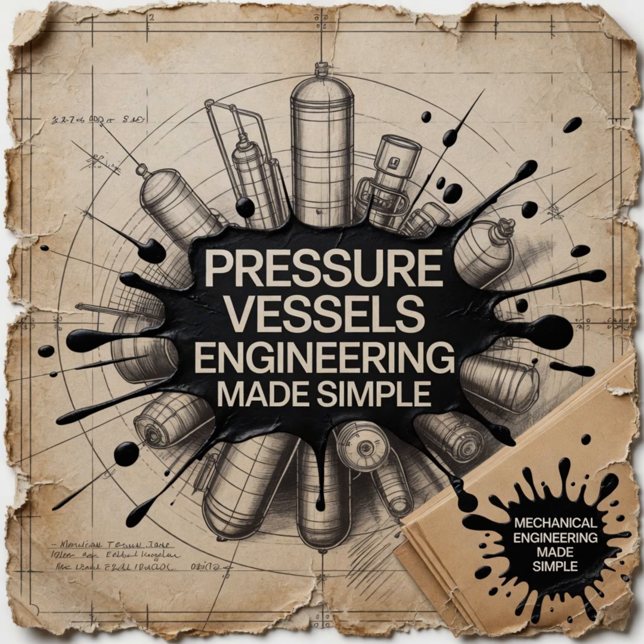Designers use stiffening rings. These are heavy steel I-beams or thick plates welded edge-on around the outside circumference of the vessel. What do those rings actually do? What these rings do is effectively break one long, mathematically vulnerable cylinder into a series of very short, incredibly stiff cylinders. The short distance between the rings prevents the buckling wave from ever forming. But there's a massive red flag on the shop floor regarding these rings, right? The placement isn't arbitrary at all. Oh no, it is a cardinal rule of fabrication.